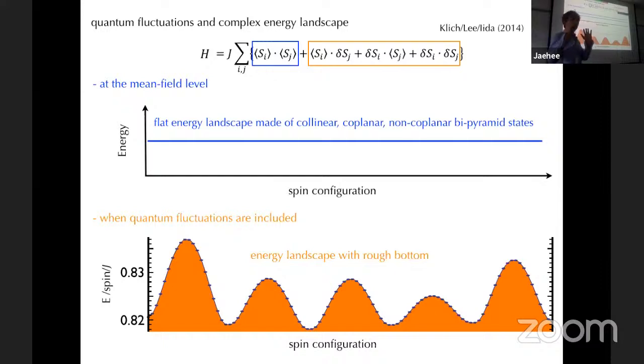As long as each tetrahedron has zero moment, total zero moment, right? On the other hand, we have to consider this quadratic term. If you consider the next order term, then this flat degeneracy will get lifted, of course. And so we have this roughness in the landscape. We'll have a global ground state, of course. And this is basically the root 3 by root 3 structure of the triangular plaquettes, in fact.